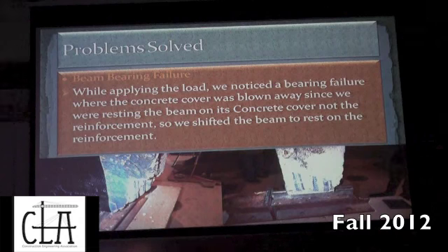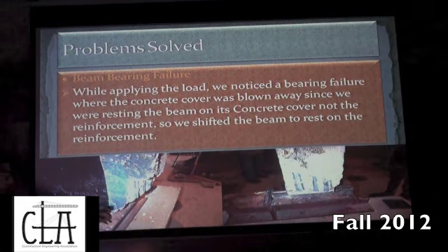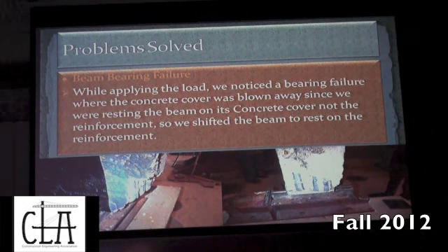The beam bearing failure. While applying load on the beam, we noticed the bearing failure from both sides of the beam, from the 2 edges. As you can see here, this is because we accidentally applied the load on the concrete cover, not the reinforcement. So to correct these mistakes, we shifted it on the reinforcement.